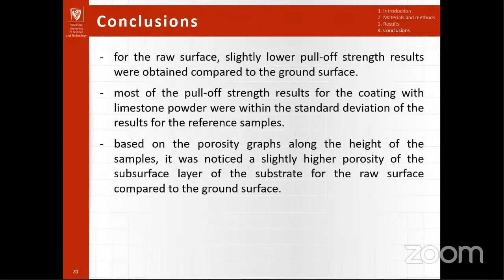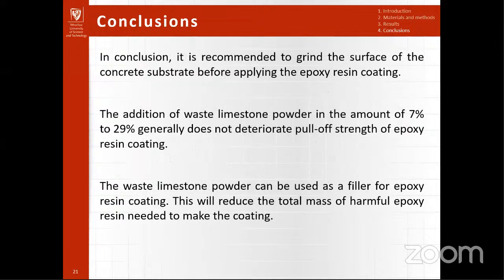Most of the pull-off strength results for the coating with limestone powder were within the standard deviation of the results for the reference samples. Based on the porosity graphs along the height of the samples, it was noticed a slightly higher porosity of the subsurface layer of the substrate for the raw surface compared to the ground surface. In conclusion, it is recommended to grind the surface of the concrete substrate before applying the epoxy resin coating.